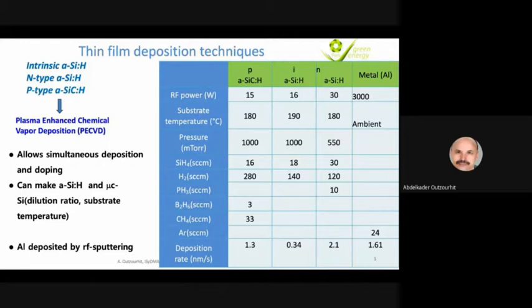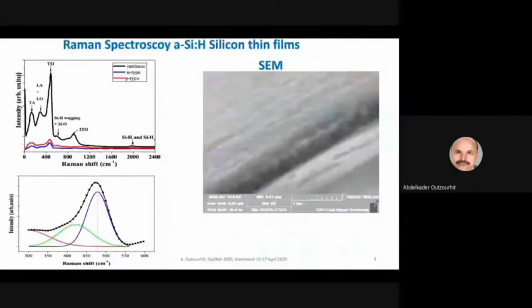Okay, so then I'll just now present some of the results that were obtained on these films using Raman spectroscopy. As you can see in this figure here, the Raman spectra of the 3 films, either the intrinsic, N-type, and P-type films, are dominated by this transverse optical mode, vibration mode of the amorphous network of amorphous silicon. In addition, we can also observe some of the peaks here that are due to the transverse acoustic and also the longitudinal optical mode.